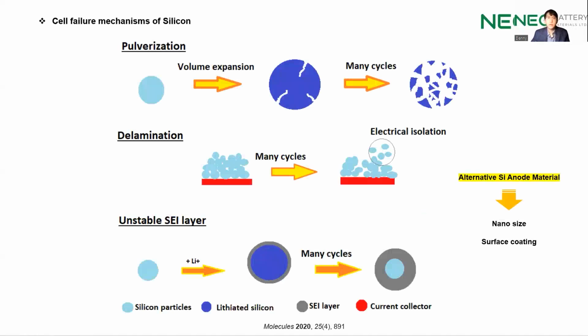So silicon has a theoretical specific capacity of up to 4,200 milliamp hours per gram. You don't have to think of milliamp hours per gram as complicated; it's just a unit of how much capacity of lithium ions can be stored per weight in the silicon. So 4,200 milliamp hours per gram as an anode material is 10 times higher than the conventional graphite counterpart, which is only 370 milliamp hours per gram. So this has triggered strong scientific and theoretical interest in the industry.